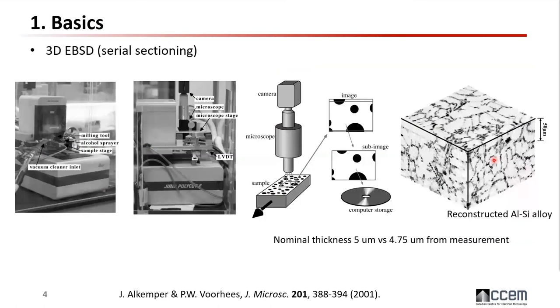How can people access the third dimension of their image? Here is an example from early development. The sample is mounted on a stage with a polishing tool — you spray alcohol, polish, clean with vacuum, then put it onto the camera and take image after image to build a 3D stack. This is more of an optical contrast approach rather than EBSD — for example, here is a reconstructed aluminum-silicon alloy showing different phases. However, the question is how precise the sectioning is: an X-ray measurement with nominal thickness of 5 microns might give you 4.75 microns in reality, so it's not well-controlled.